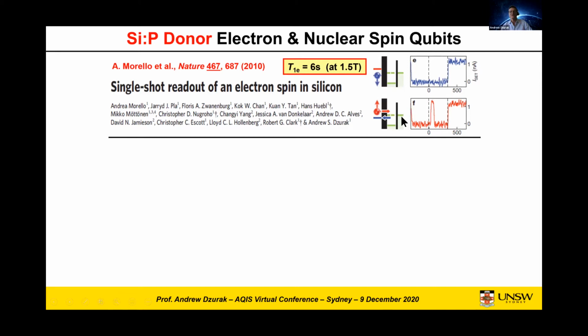And so what is done in this experiment is that the electron is loaded with a random spin, and then the Zeeman energy levels are positioned so that they straddle the Fermi energy in the island of this single electron transistor. And what that means is that only an electron spin up has sufficient energy to tunnel into the island of the single electron transistor, or SET for short. Now, when that happens, that then allows current to flow through the transistor, and so we see a sudden uptick in the current of the transistor, which can be monitored.